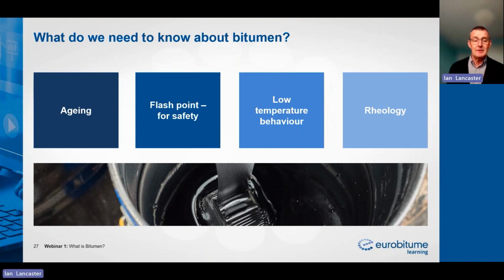And so at a later stage, there are other things that we will need to cover. We need to think about the aging of bitumen. It's an interesting material, bitumen, because it's affected by heat and it's affected by air. And so every time we move it about, we run the risk of incorporating heat and air and aging the bitumen. And what we need to know is how much does the bitumen age in those processes. And we can measure the aging on a short-term effect to give an idea of how the bitumen will be aged in, for example, an asphalt mixing plant.